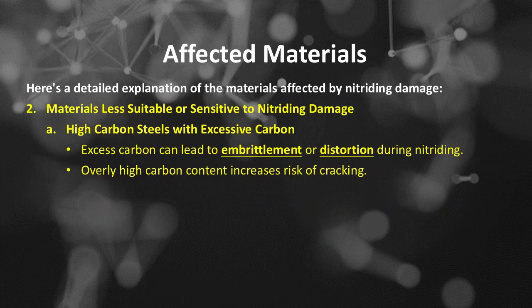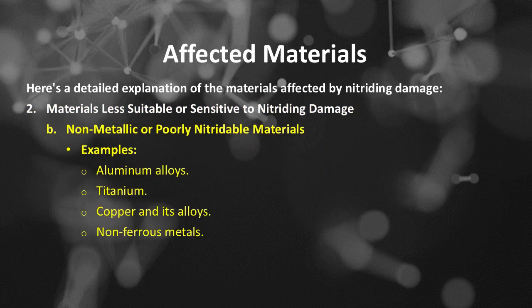Number 2 of the materials affected by nitriding damage is materials less suitable or sensitive to nitriding damage. Number A, high carbon steels with excessive carbon. Excess carbon can lead to embrittlement or distortion during nitriding. Overly high carbon content increases risk of cracking. Number B, nonmetallic or poorly nitridable materials. Examples: aluminum alloys, titanium, copper and its alloys, non-ferrous metals.